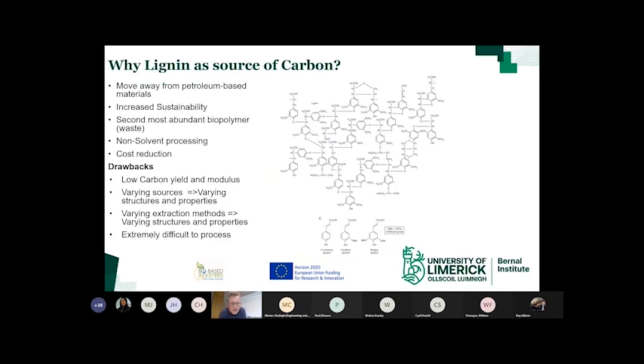So why use lignin? Lignin, as you can see from looking at the structure, anybody that's familiar with carbon fiber production, you can see all those phenolic groups. You can see straight away that this is an ideal material for making carbon structures just by looking at the chemical structure, because these rings can fit together and make a really good crystalline structure, really good for carbon. And this is the most abundant naturally occurring aromatic molecule available to us. In fact, it's the second most abundant polymer behind cellulose.